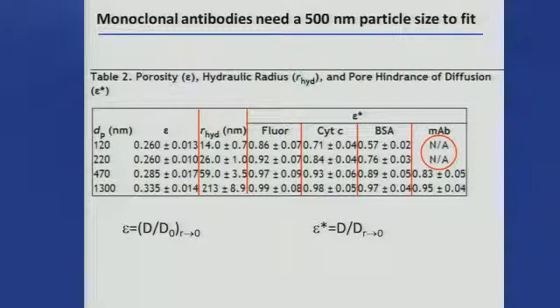And so to get a molecule into this, you have to have some free volume, or if it's a solid, the molecule won't go in. And the pore size has to be big enough for the molecule to get in. We want to use this for protein separation, and proteins can get pretty big. So this is a small molecule, fluorescein, larger cytochrome C, larger yet BSA, and then finally the thing that is very important technologically to separate today is our monoclonal antibodies, which are the biggest of all.